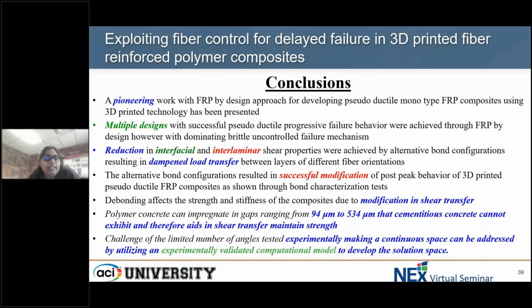So we've seen multiple designs with successful pseudoductility, and there's more progressive behavior achieved due to different kinds of bond configurations, which is completely contrary to that uncontrolled failure mechanism that we saw in FRP composites earlier. Reduction in interfacial and interlaminar shear properties can be achieved, and this reduction inherently dampens load transfer between layers, and that in turn affects how the failure mechanism is affected.